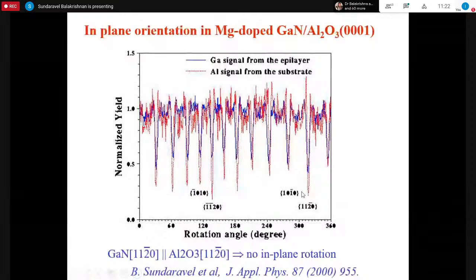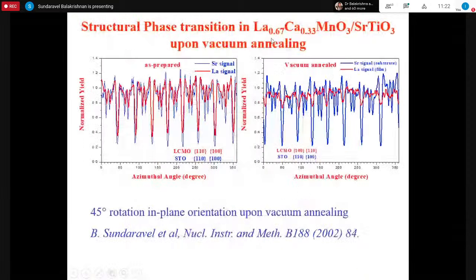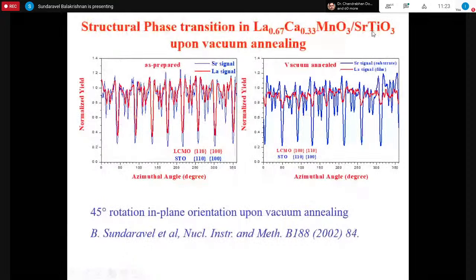And another system, if we take LCMO on strontium titanium oxide, and if we do vacuum annealing, before vacuum annealing, if you see, there is no rotation between this LCMO and strontium titanium oxide.